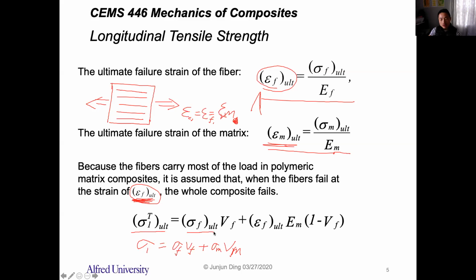So for the fiber, the fiber will withstand the ultimate stress, right? Because the fiber will fail at that time. So you have the fiber ultimate strength times the fiber volume fraction. And here, for the matrix, the stress applied to the matrix is calculated based on the strain and the Young's modulus of the matrix, because the matrix does not fail at that point, right? So this is the strain applied to the matrix. So the stress applied to the matrix will be equal to strain times Young's modulus of the matrix, right? So this will be the stress of the matrix.